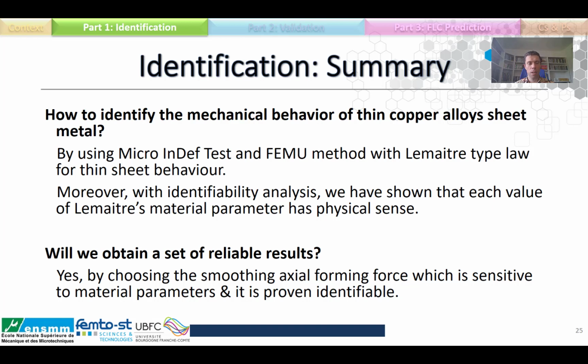At the beginning of this part, we had two questions. The first one was how to identify the mechanical behavior of thin copper alloy sheet metal, and the second one was, will we obtain a set of reliable results? The answer is that we can identify the mechanical behavior by using the Micro InDef Test and the FEMU method with a Lemaitre type law for thin sheet behavior. And moreover, we have shown that each value of the Lemaitre material parameters has a physical sense.